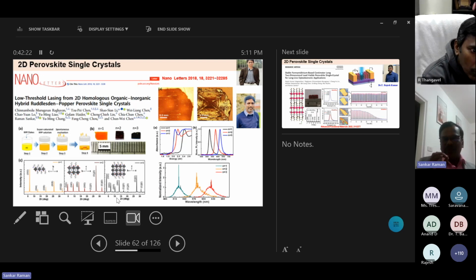The main utility of changing the number of layers is that you can tune the band gap of the material. You can clearly see the PL on the right side, for N equal to 1, N equal to 2, N equal to 3. You can tune the wavelength from 500 to 650 nanometers, and also the band gap. And we also did lasing studies, which are really stable up to room temperature.